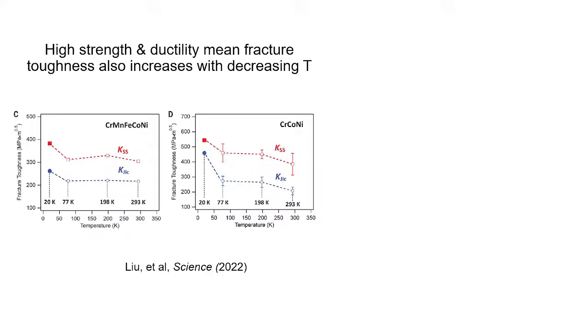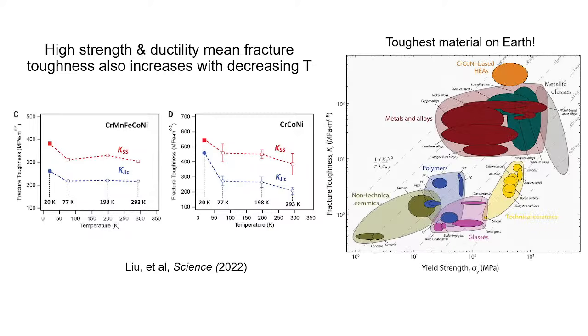And then if you plot an Ashby plot of fracture toughness versus yield strength, these are the high entropy alloys. These are the toughest materials on Earth, right? So, I mean, you can compare to any other system that people have tested, and they're by far the toughest, approaching 500 MPa square root meter.